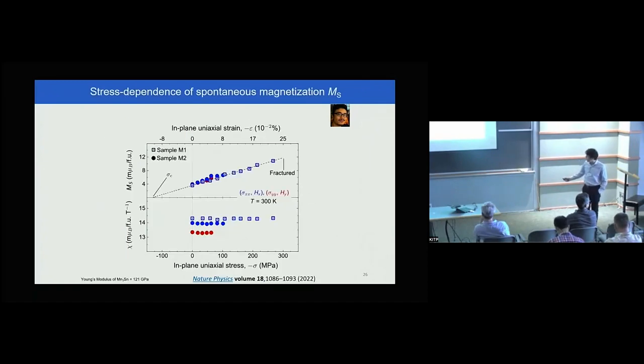And if we summarize this, it looks like this. The spontaneous part of the magnetization is linearly increasing as a function of stress. Susceptibility remains the same. And this is exactly what you expect for piezomagnetism. And this linear coefficient as a function of uniaxial stress tends to be quite large. And this is somehow very close to the maximum size known for the antiferromagnetic insulators. Okay,